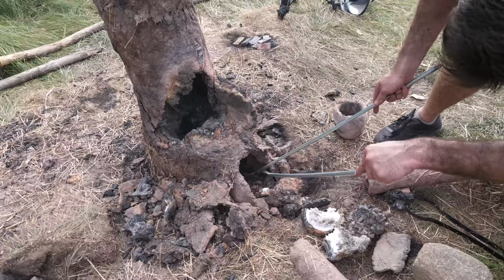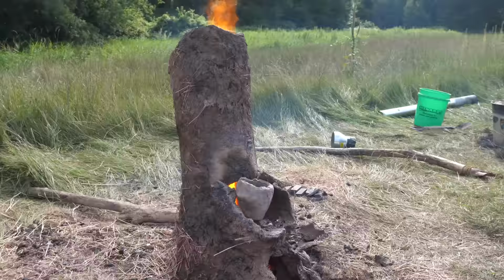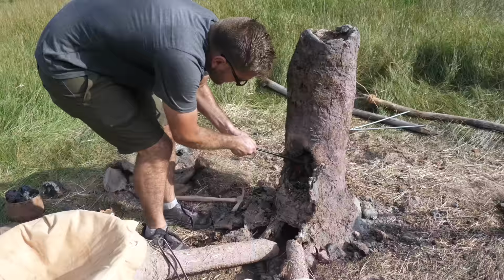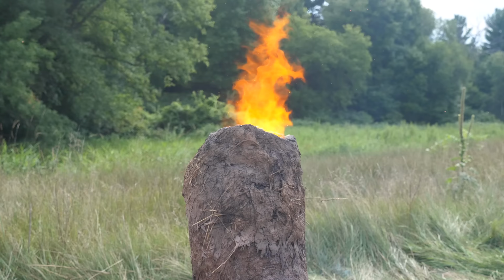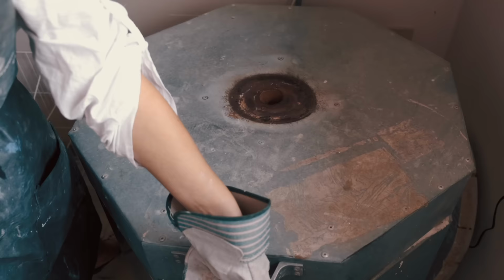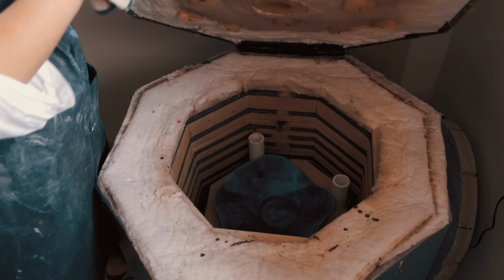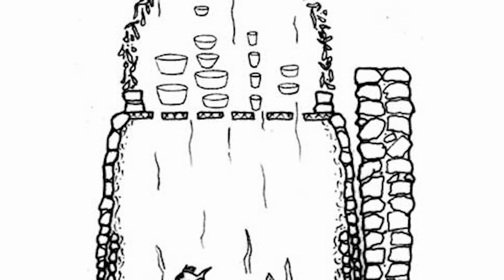The failure of the first attempt seemed to be primarily because of the very direct and uneven heating that was hitting the crucibles, causing them to crack and break on the exposed side, while not reaching the high temperature on the other side. So for the next design, I want to try getting the crucible directly over the heat with some amount of separation, hopefully producing a much better result. Similar to this depiction I found of a cupola-style kiln, with the crucible sitting on a grate directly above the heat source. I'm not sure why they put fish in there.